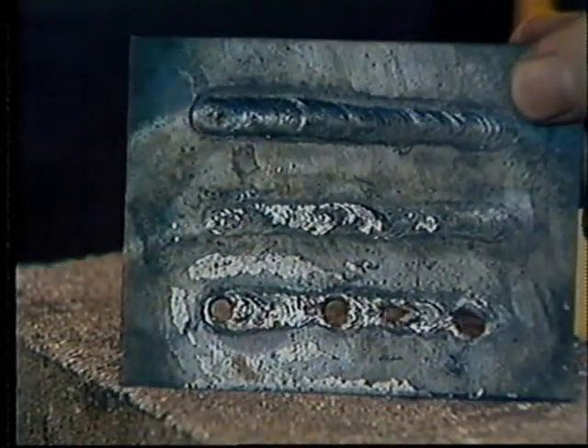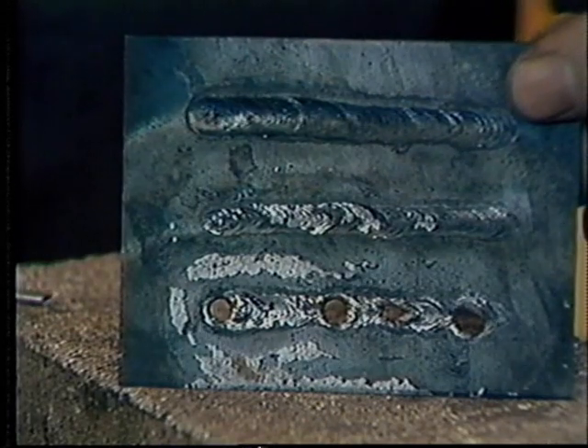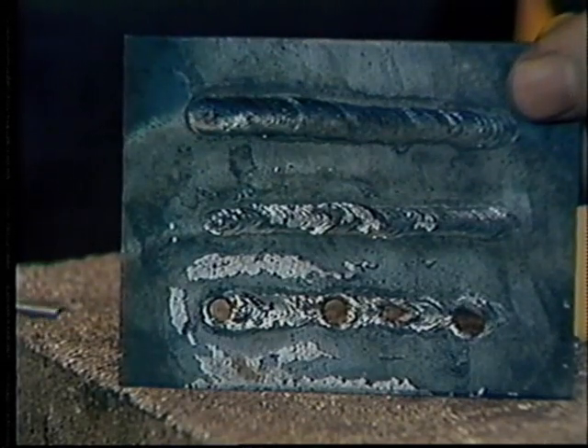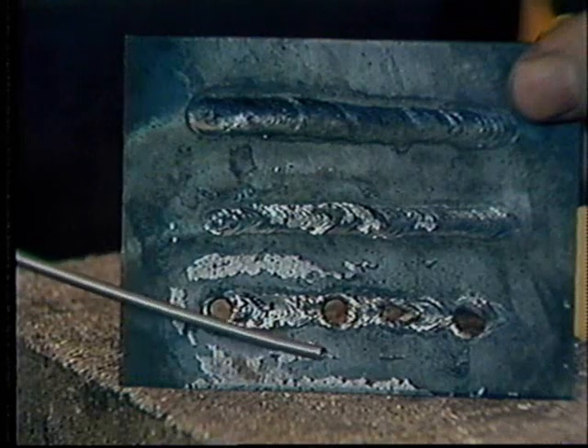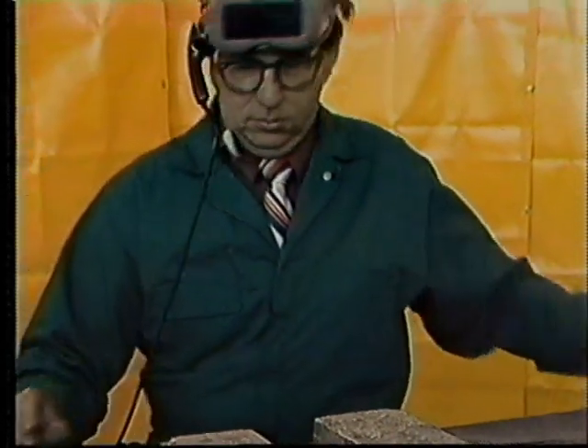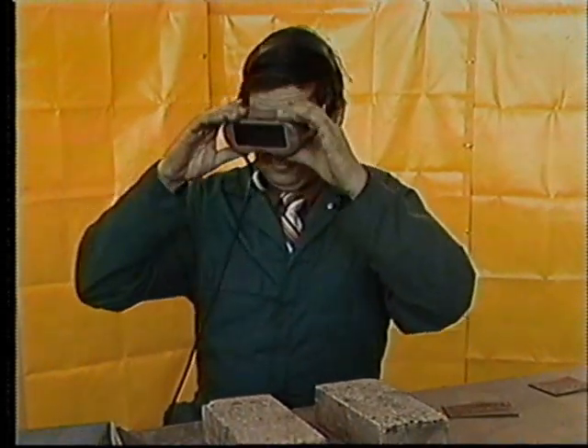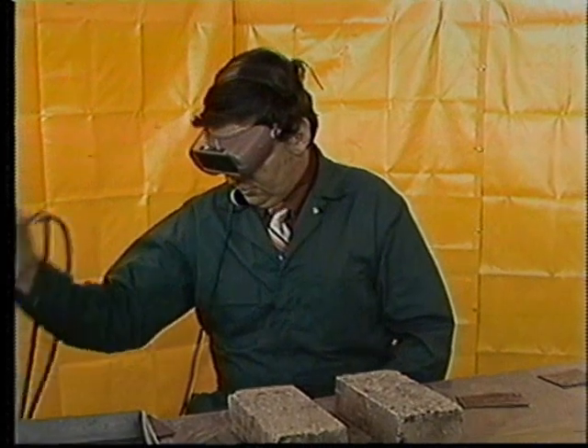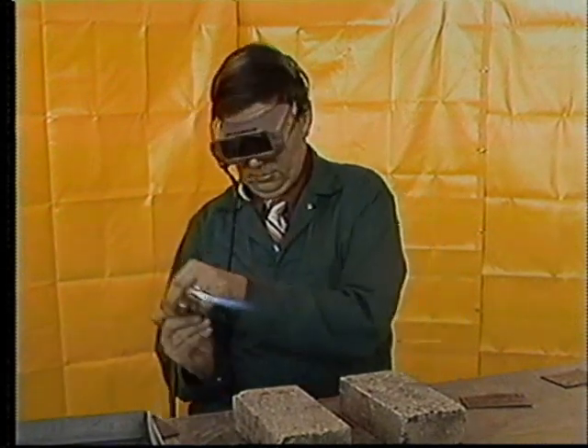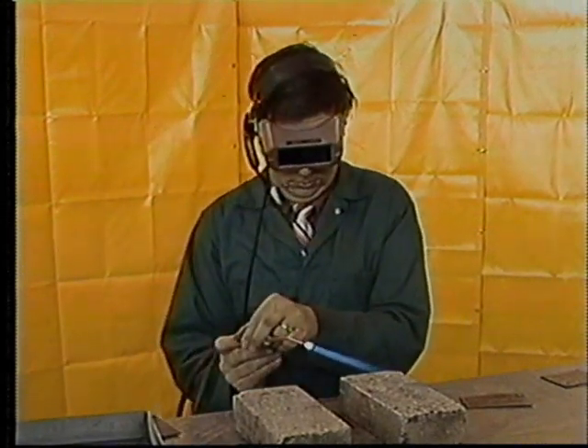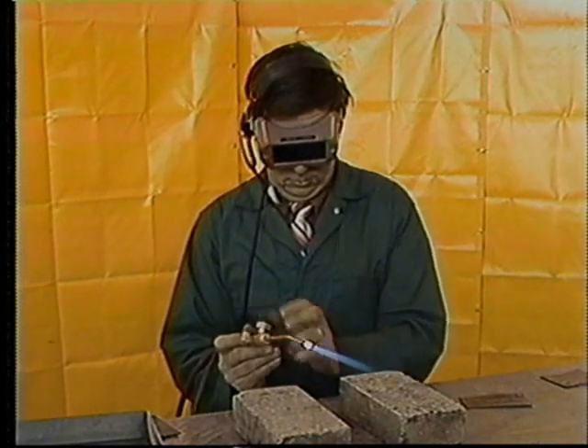Why the holes in the bottom one? Those are caused from too much heat. They are a result of overheating the puddle and blowing a hole through the base metal. And that, other than being a bad weld, completely destroys the metal? It doesn't completely destroy the metal, but it makes it a part that then needs to be repaired.